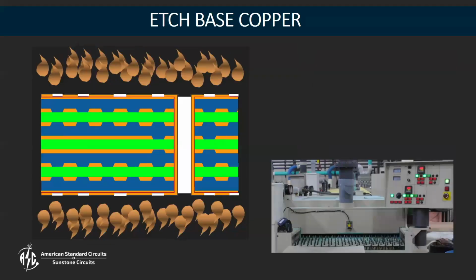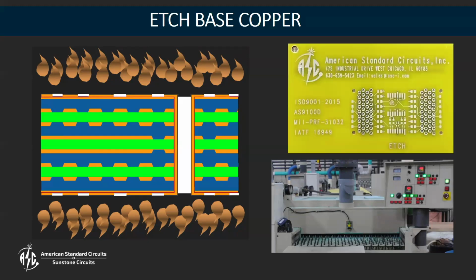Goes through the etching process, basically the same as I talked about before. Generally, an ammoniacal etch is used for outer layers. And we are going to etch down to the laminate, creating those pads and traces, isolating where we need to.